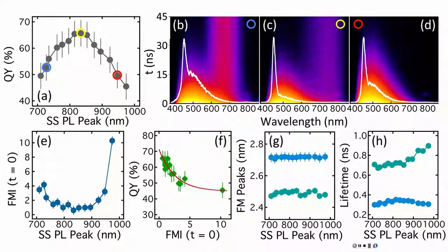It does coincide? Yeah. If you look at silicon, like if you look at the absorption spectrum, it should change with your confinement, right? Well, that's a question I have. It doesn't. I changed the size of the nanocrystal, and it's still the same. The position of the peak stays the same.